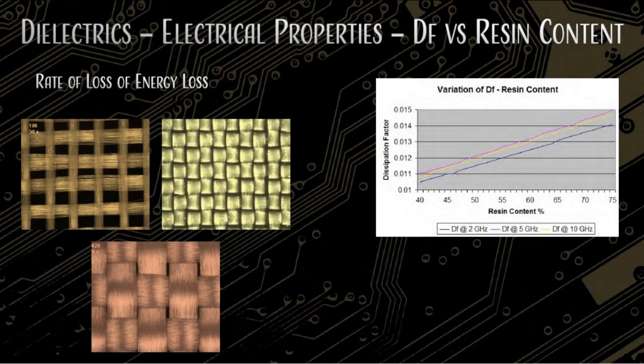So if you have a high-speed design, really what you're looking at is something with a tight weave, so that you've got less epoxy, more fiberglass, and a more consistent dielectric constant. That'll give you a more consistent impedance as your signal travels. Something to keep in mind when you're creating these things is the prepregs have a lot of epoxy. Cores don't. So you usually want your signals to travel and be coupled between adjacent layers on a core, rather than, you know, if you're doing a cap construction or something like that. Would you agree with that, Teresa? Yes. Yes, I will.